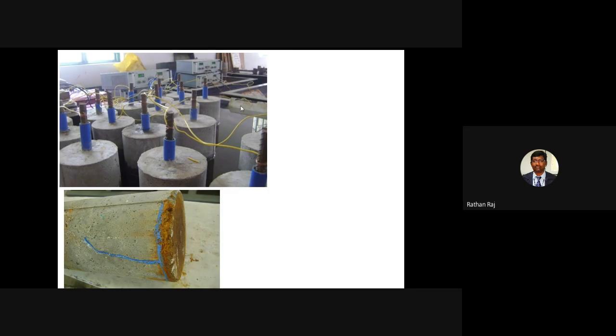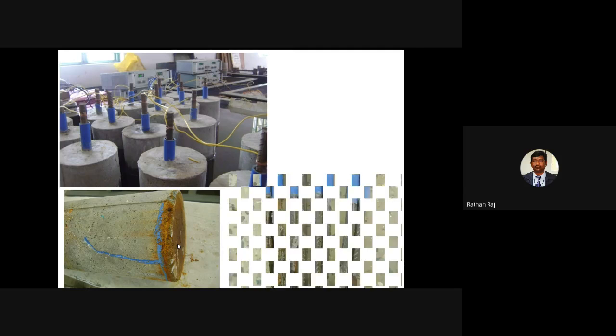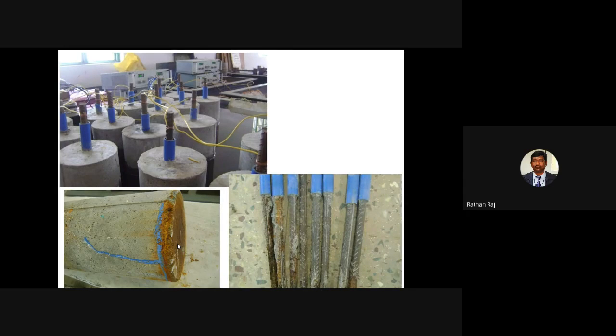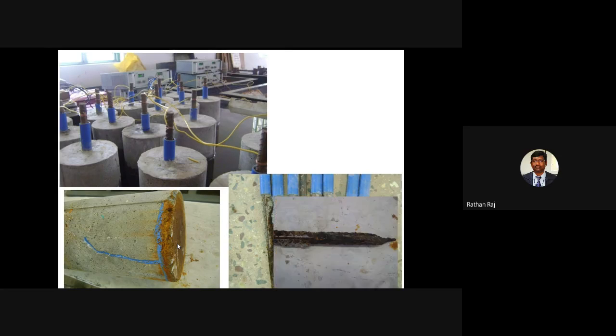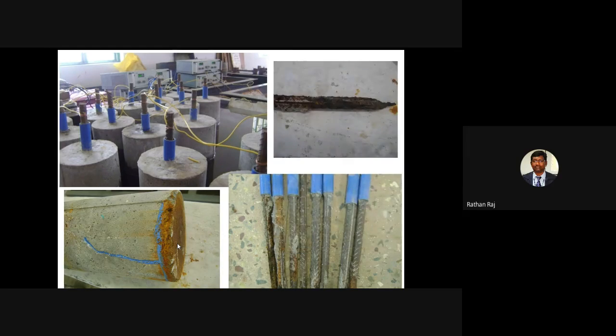So after 15 days, the corrosion takes place, forming and developing cracks on the concrete. See at the bottom, the color change shows that there was corrosion. After that, using a split tensile method, the concrete is carefully split and the reinforcement is carefully taken away from the concrete. These are the reinforcement bars, particularly in the most severe condition. This is the corroded rod after 15 days of accelerated corrosion.